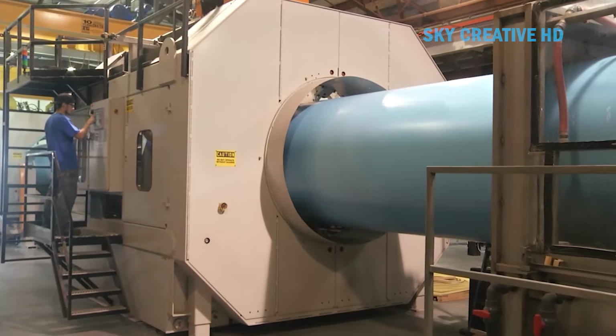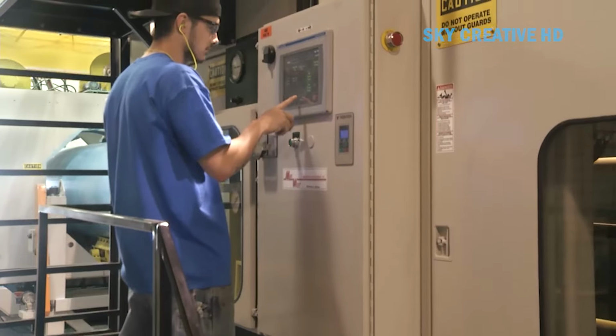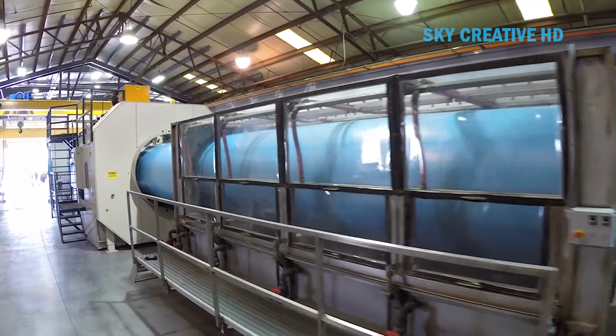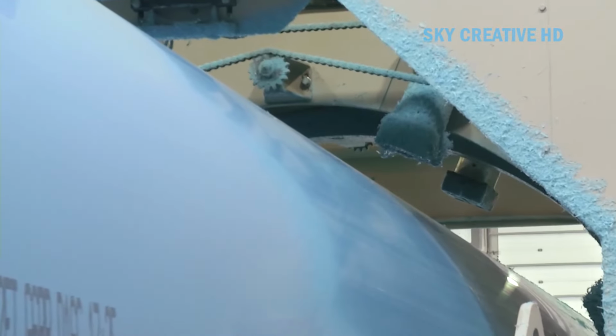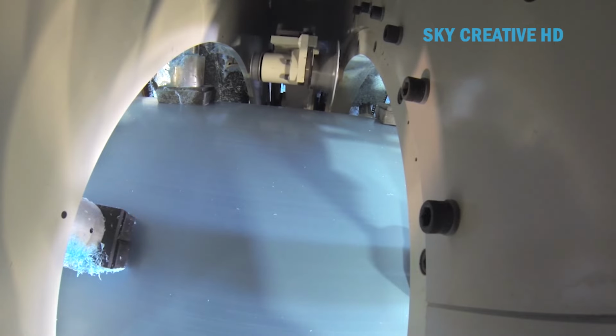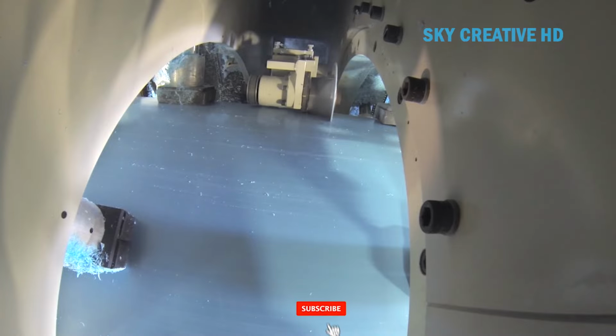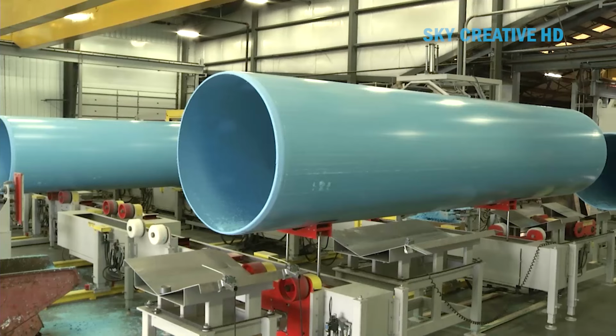The blended material feeds into a massive twin-screw extruder, the heart of the operation. This machine is a beast. Imagine a barrel 20 feet long with two intermeshing screws rotating inside. As the PVC travels down the barrel, multiple heating zones gradually raise the temperature to around 400 degrees Fahrenheit, melting the plastic into a homogeneous melt. The twin-screw design provides superior mixing compared to older single-screw extruders, ensuring consistent material properties throughout.